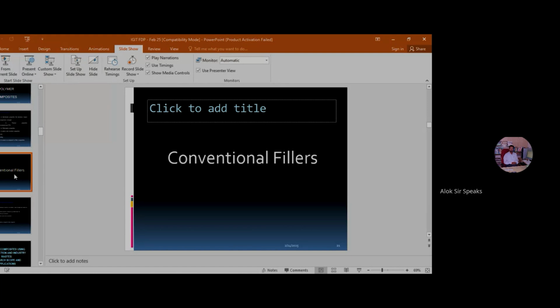So by replacing the conventional fillers, for example, if you make a polymer composite with 30% boron nitride or 25% boron nitride in it, suppose you make a composite of epoxy and hexagonal boron nitride, and we have made this particular composite for electronic applications. Now if you do this, then what will happen? Whatever will be the cost of the composite, if you replace this boron nitride by some conventional or non-conventional filler, that means waste filler, then the cost will drastically reduce, because in boron nitride epoxy composites, 60% of the total cost of the composite goes to the cost of the particulates or the filler. Okay, there is no fiber here, only filler.